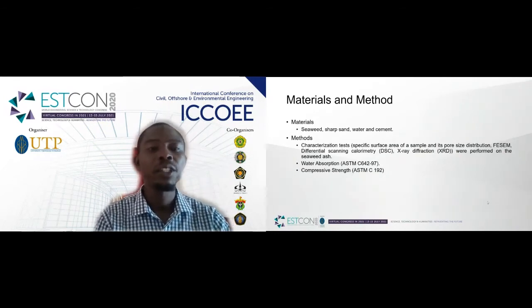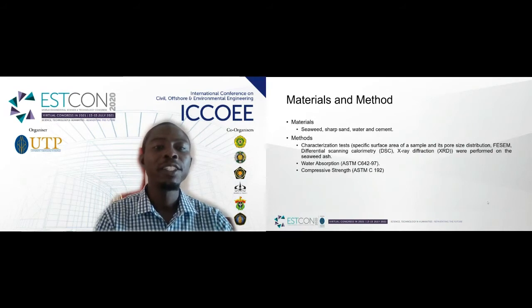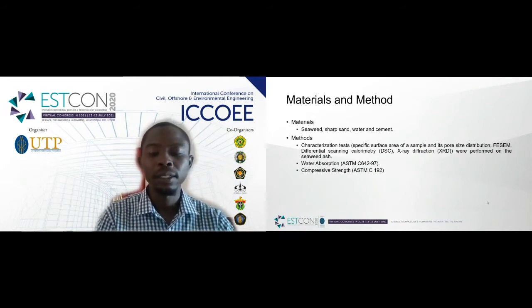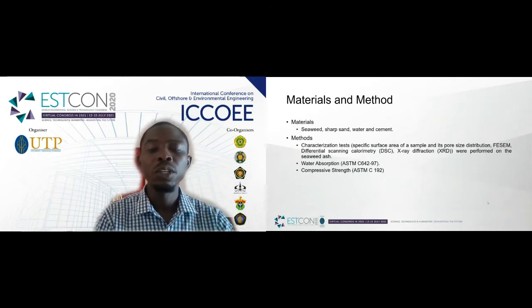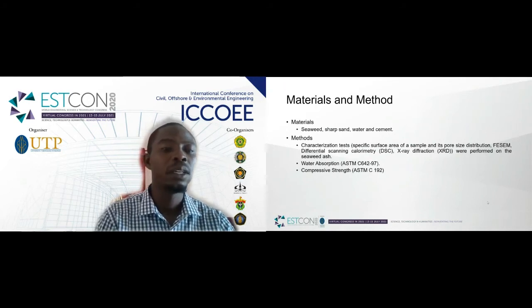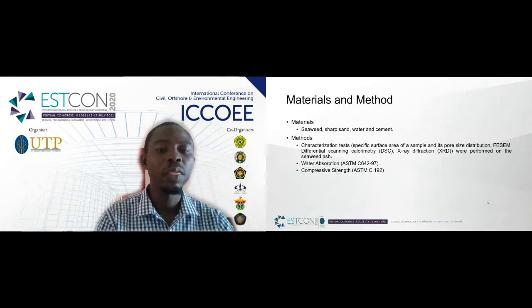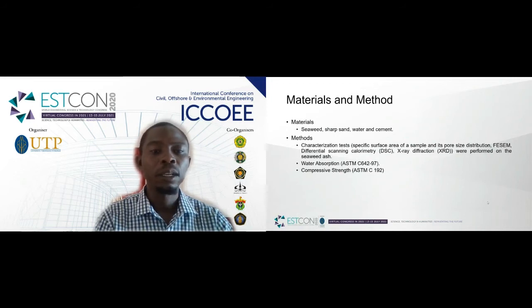Materials and methods. The materials used in this research include seaweed, sharp sand, water, and cement. The method. Point number 1, characterization tests, which include specific surface area of the sample and its pore size distribution. FESEM, DSC, XRD were performed on the seaweed ash to determine its suitability as a replacement material. Water absorption test was conducted according to American Standard Test Method C642-97. Compressive strength test was conducted according to ASTM C192.